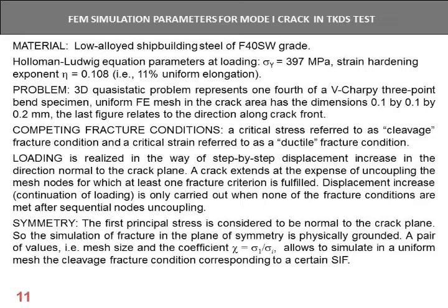Displacement increase, continuation of loading, is only carried out when none of the fracture conditions are met after sequential nodes uncoupling. The first principal stress is considered to be normal to the crack plane, so the simulation of fracture in the plane of symmetry is physically grounded.